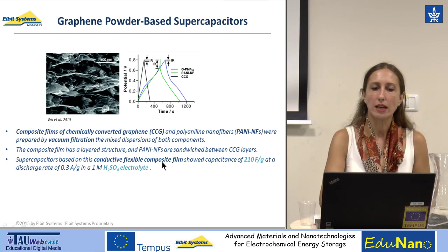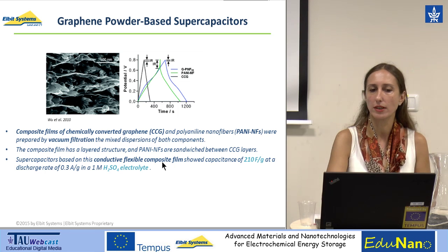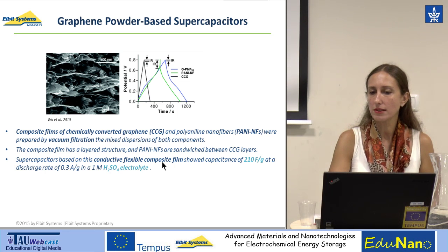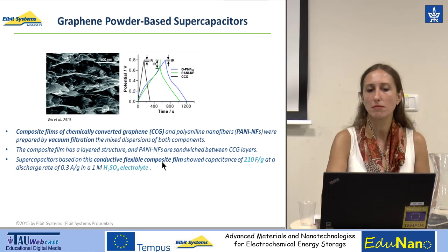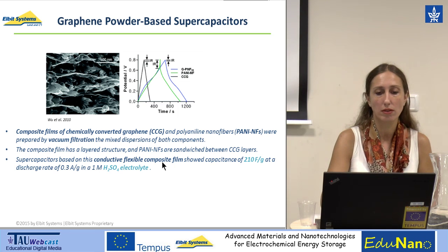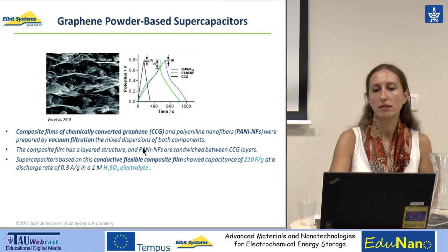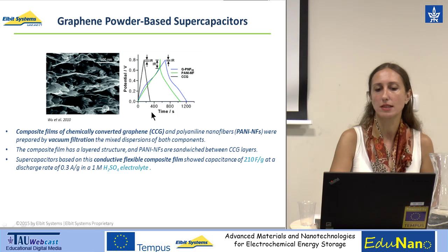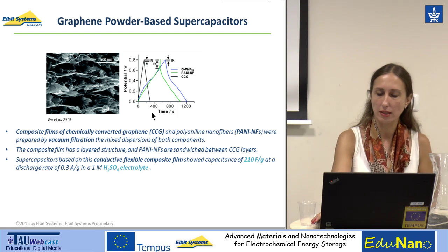So the supercapacitors based on this conductive flexible composite film showed a capacitance of 210 farad per gram at a discharge rate of 0.3 ampere per gram, and they were tested in an aqueous 1 molar sulfuric acid electrolyte.